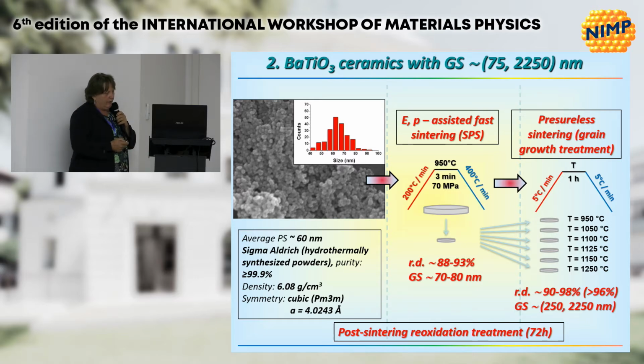With respect to other studies, we preferred to keep the same type of powder and to obtain an intermediate range of grain sizes by using a two-step sintering method. One is a field and pressure assisted spark plasma sintering, in which we used the same parameters for all the samples, because spark plasma sintering is a highly non-equilibrium process, and we wanted to start at least with the same level of densified ceramics for the second step, which is a grain growth pressureless sintering step, allowing us to obtain the desired range of grain sizes. In the first step, we just consolidated the powders, because the grain sizes obtained are about the same.